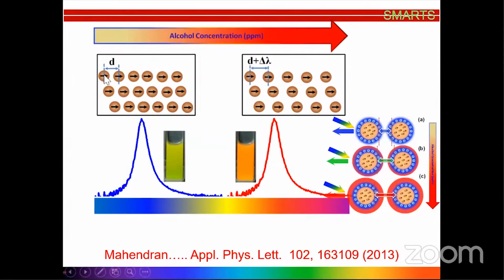So when you create this kind of ordering, you have a Bragg peak, and now if you introduce surfactant, alcohol or other molecules into the system, what happens is the electrostatic interaction or the conformation of polymer, if you use a polymer to stabilize these emulsion droplets, then the inter-particle spacing, the d-spacing, is changing by delta lambda. So that can be manifested spectroscopically. All you need is a spectrograph. A pocket-sized spectrograph can do all the jobs.